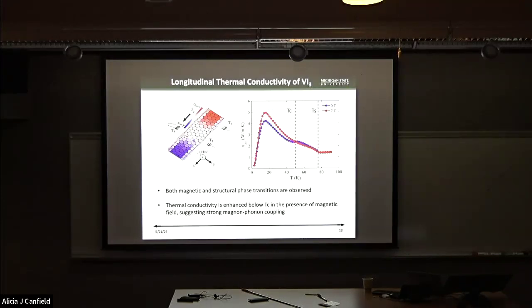Related to the first question, no, we did not encapsulate this system. And this system is very air sensitive. So as I mentioned, what we did is we make the device inside the glove box, and after we finish fabricating the device, we immediately put it into the PPMS chamber within maybe one minute. Hopefully by doing that, we can avoid exposing the sample to air and degrading the sample.